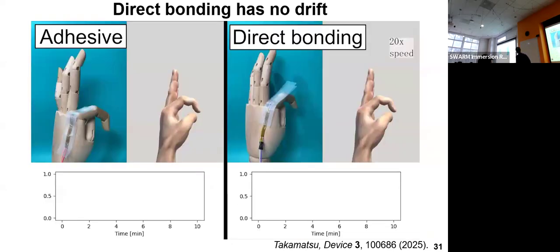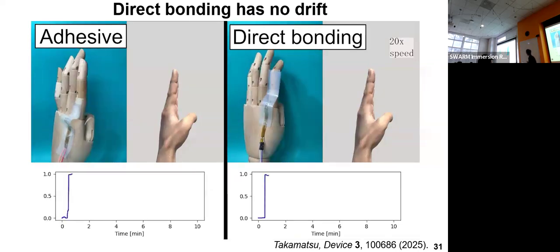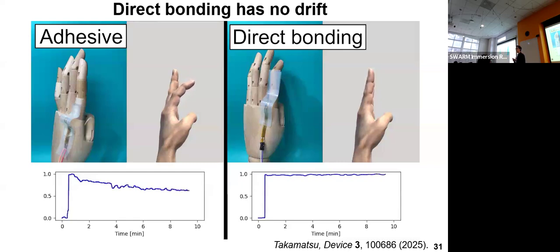And then the important benefit is that we don't use any adhesives. So there is no relaxation of the strain sensors. If we use adhesives, the strain sensors are relaxed, so the signal is changed. But if there is no adhesive, such a drift is not observed. So this is a very, very important aspect when considering practical applications of strain sensors, for example, real applications.